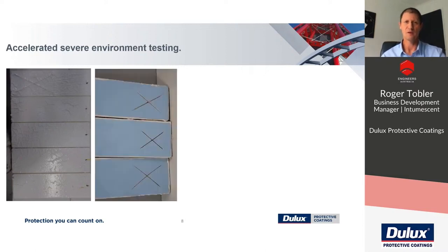And these panels had 200 hours of exposure. You'll see the one with a scribe at the top, that's an X mark back to bare metal. That's had the most amount of damage. And you can see that in the flakes and the cracks in the top coat. But all through you can see this product has been compromised. And we're testing a water-based intumescent far beyond the C2 environment here. So it's to be expected that it'll fail really early because it's tested where it shouldn't be going.